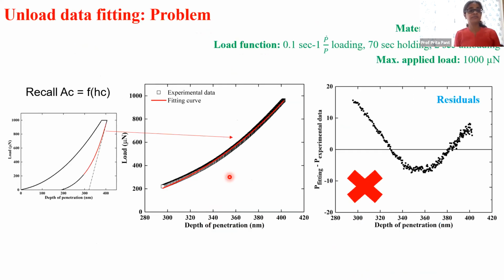Now, this calculation of area of contact, okay, could there be problems in fitting, right? Because if you remember, the area of contact is a function of contact depth, right? The equation that Oliver and Pharr had given us. And my contact depth, I'm getting from this, right? I measure S and then I subtract this epsilon, some 0.75, into P max by S from my H max to get my depth of contact.